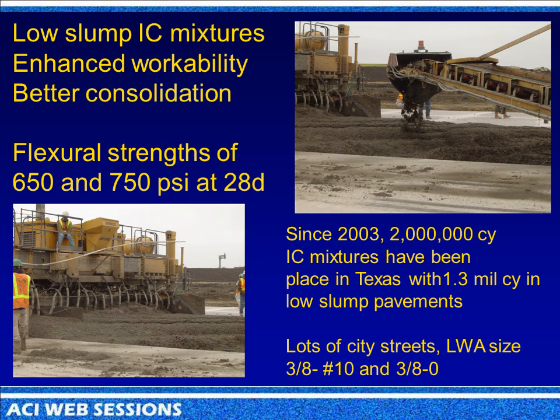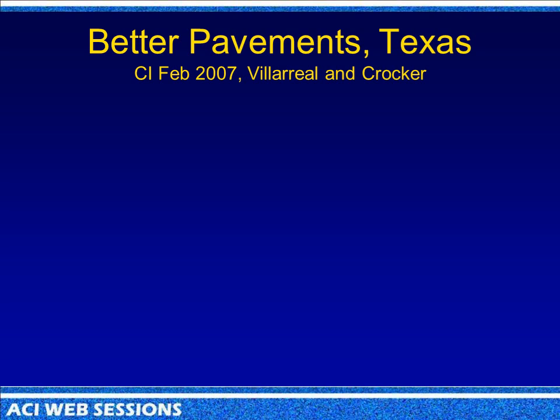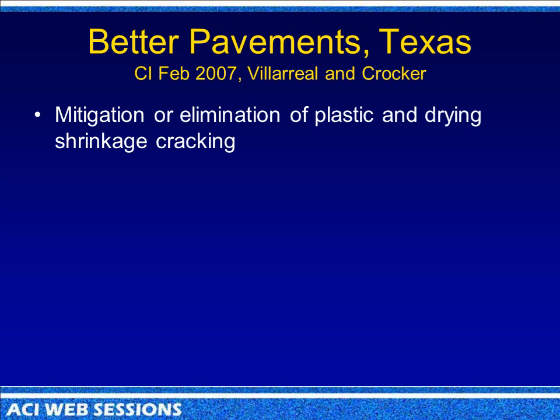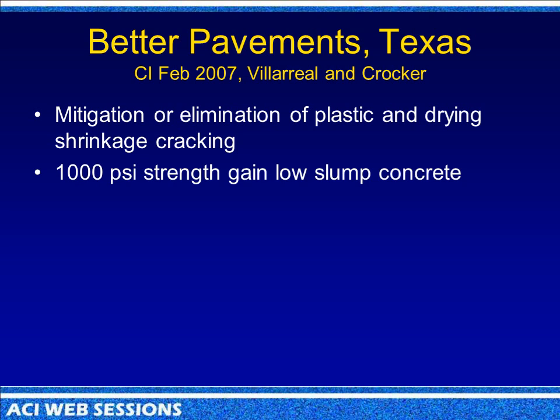And I don't claim to be the expert. They say I'm a philosopher with a concrete degree. But this is what they're saying down there. And this is what the people in Texas are going to tell you. They say they mitigate or eliminate plastic and drying shrinkage. That's why they like it. They're getting about 1,000 PSI strength gain. And that's probably because part of it is they're getting a better gap grading. They're filling in for gap grading.